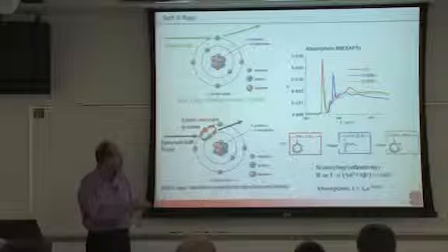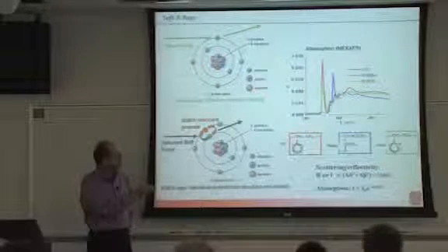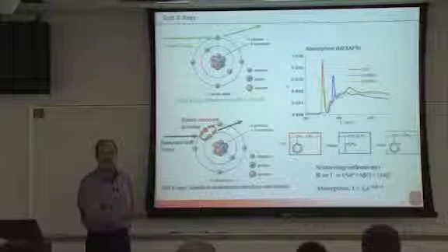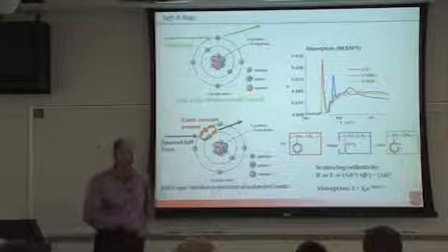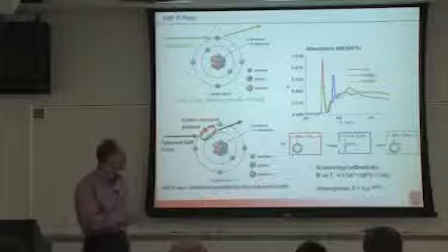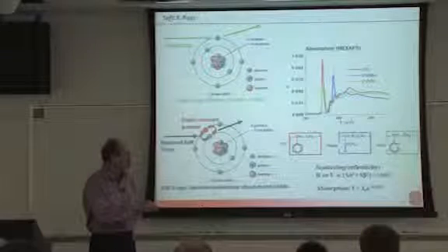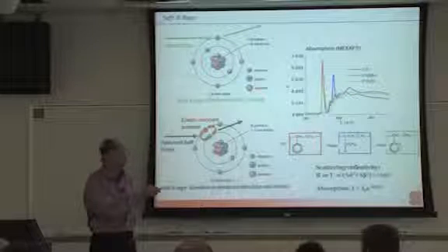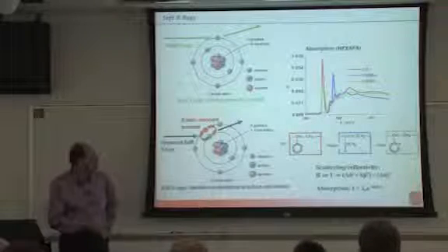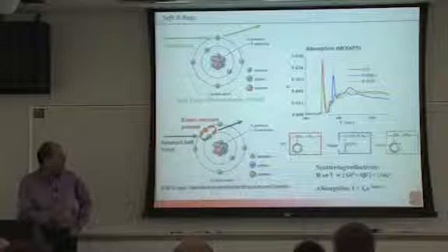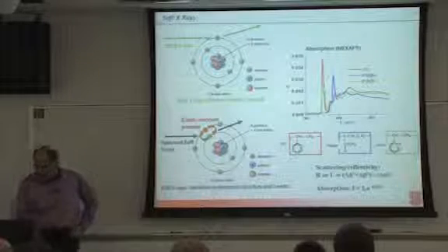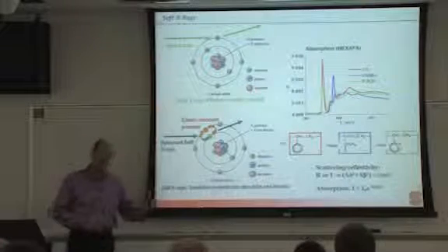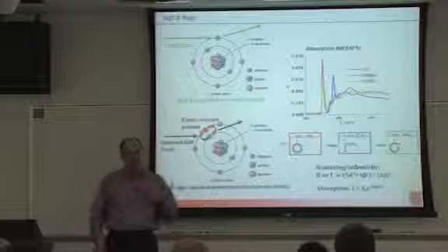And then if I go to PMMA, this peak is shifted a lot. The unsaturation is next to an oxygen atom, so there's both initial and final state shifts. Even if I just change one of the carbon atoms in the aromatic ring, I completely change the structure of my pi star, the unoccupied pi levels, and that changes the spectroscopy. So this is a very rich method in many ways.